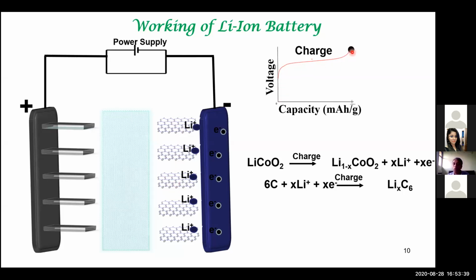So I have raised the voltage. I have removed the lithium from the lithium cobalt oxide, moved it across the electrolyte, and intercalated it into the graphite, and I have formed this compound. So this is at a high energy state, and I have used an external power supply to charge the battery.